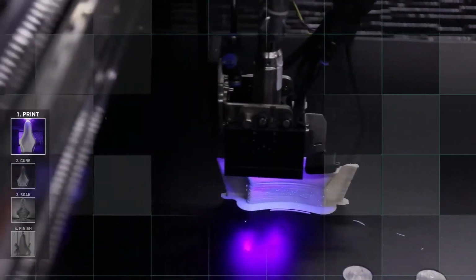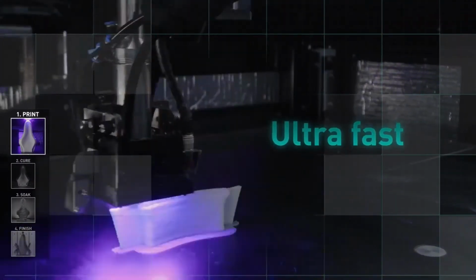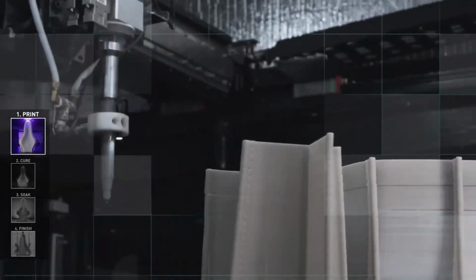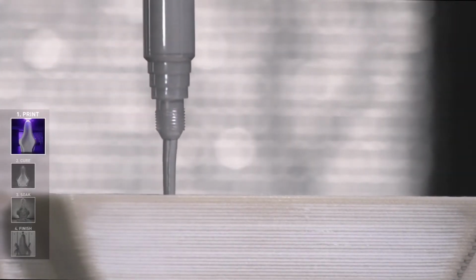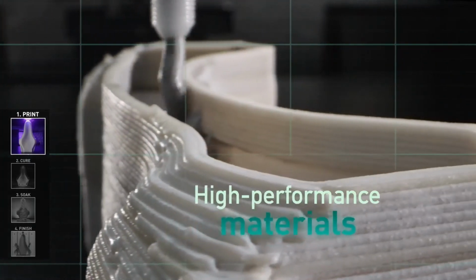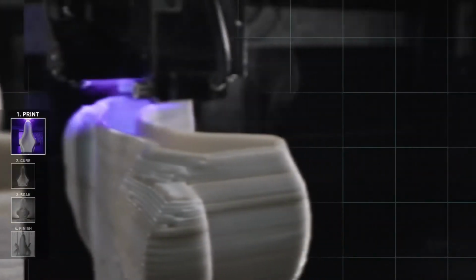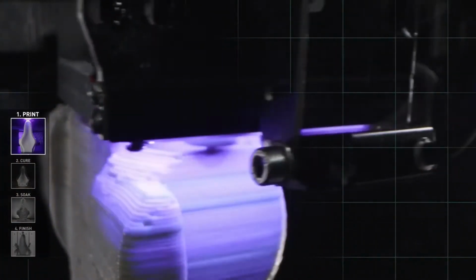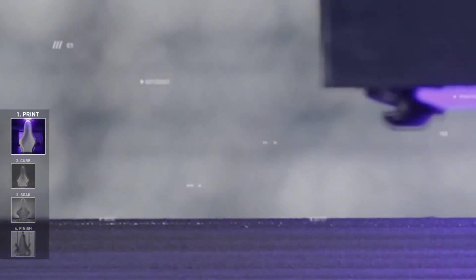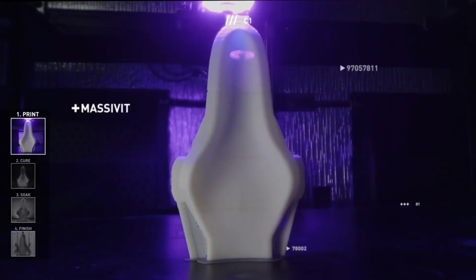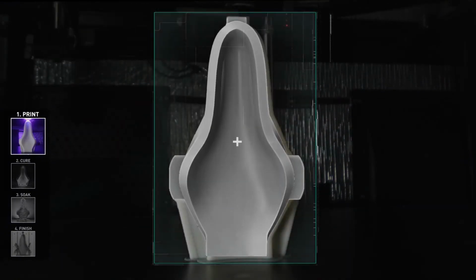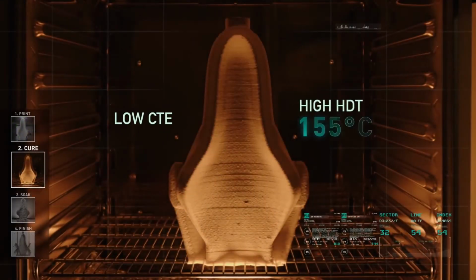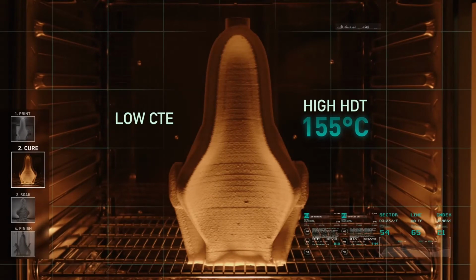Based on an initial CAD design, the first head 3D prints an outer sacrificial shell at high speed. The second head intermittently casts a thermoset material into that shell as it builds. The shell is comprised of two thin walls made of water-soluble photopolymer material that polymerizes instantly under ultraviolet light. The thermoset material forms a solid, isotropic mold. The mold can then be post-cured in an oven to improve its mechanical properties at elevated temperatures.